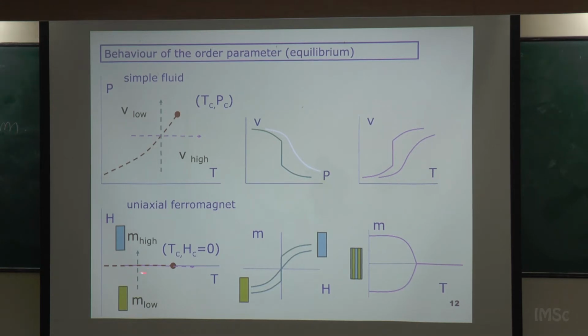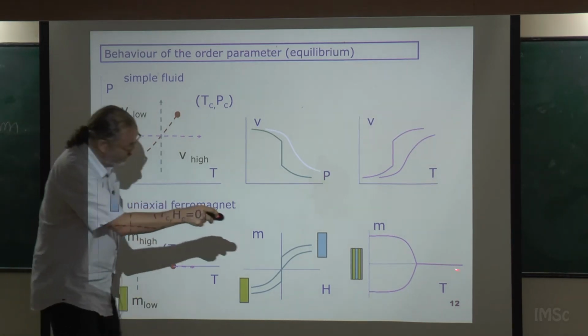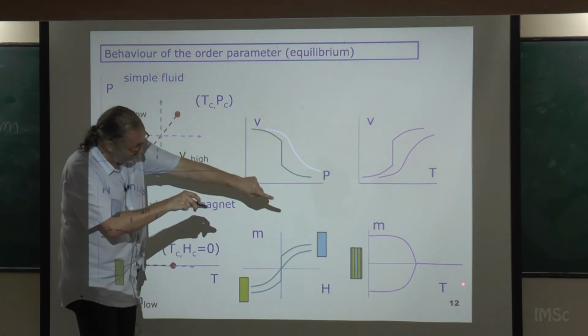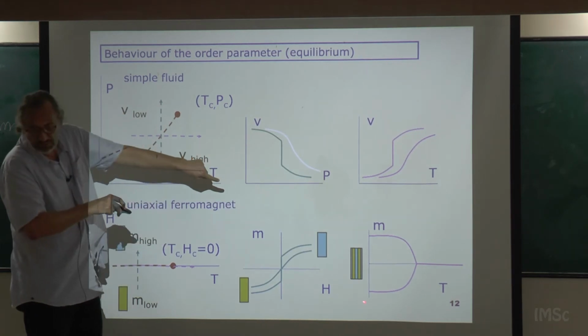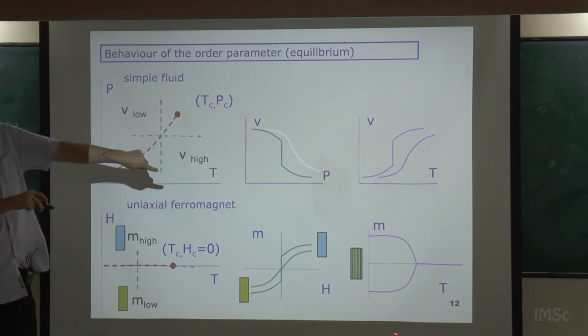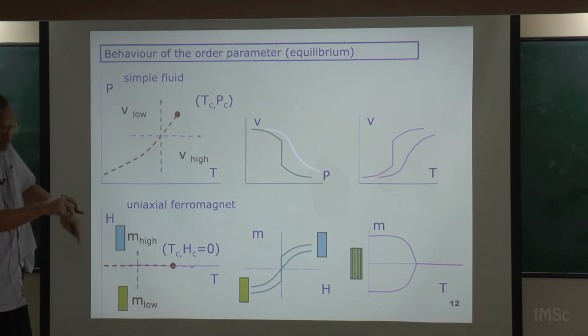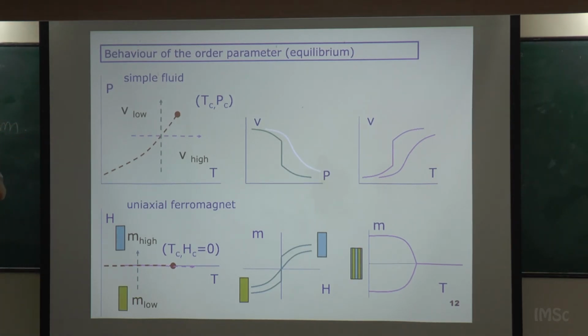If you go like this and you decrease the temperature at zero field, you find something like this here. So you have zero magnetization, and suddenly two branches develop, equally symmetric. So what happens is that the system fills up with domains of the two magnetizations. So you can have two values. This is what happens in a first order phase transition.